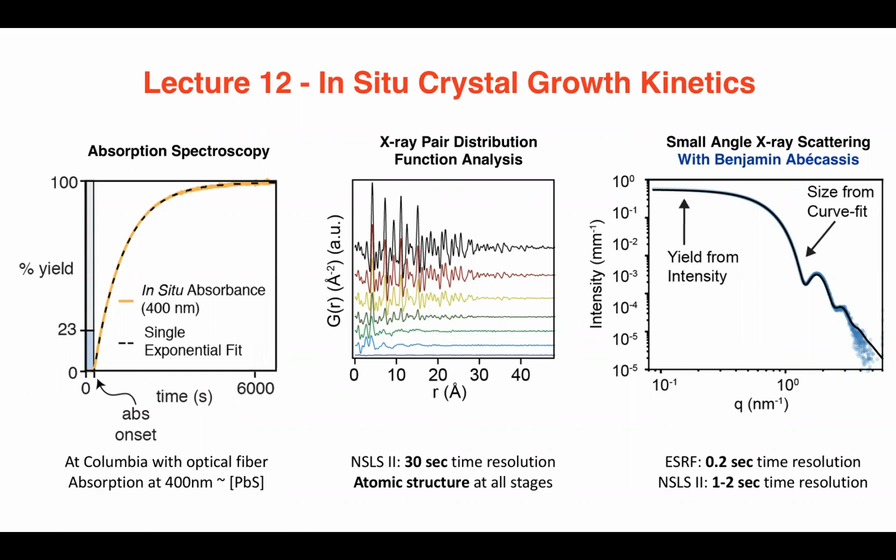trying to fit these scattering patterns to monitor crystal size. You can also take X-ray small-angle patterns, here's a real small-angle pattern from crystals grown by our group. And you see it's flat out here, which shows that you have small objects that are well separated from each other. And then out here in the lower region, you get these oscillations. And so fitting this stuff will tell you about the size of this region. And the total amount of scattering will tell you the intensity. So you can get real quantitative measurements this way of size, polydispersity, and yield by modeling patterns of this kind.